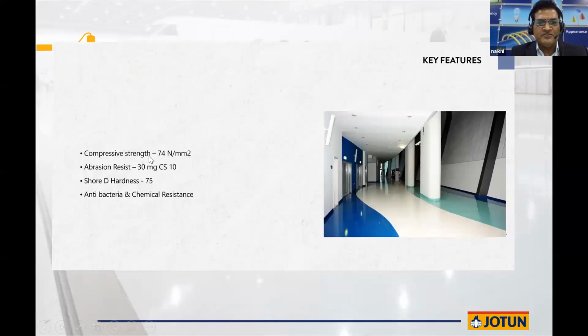And it has a compressive strength of 74 Newton, which is almost 2.5 times the normal compressive strength of concrete. A shore hardness D of 75, which is extremely high. It's antibacterial and chemical resistance certified.